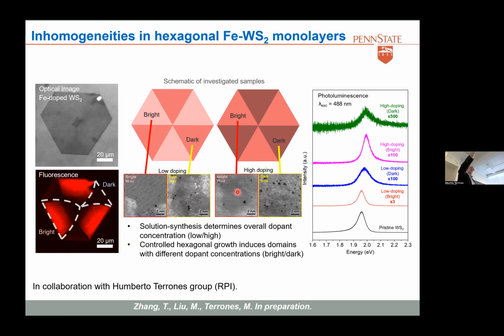So you have a hexagonal or close to a hexagonal monolayer where you have photoluminescence everywhere, but you have bright spots here and you have darker spots here. And one thing that we notice is that the bright spots have almost no dopants, and the dark spots will have more dopants. So you have more iron here. And this is with the low doping case. In the high doping case, the same. So you have the darker spots have more iron. So basically you are doping with iron, or you're alloying with iron here. And then you have this growth in these hexagonal alignments.